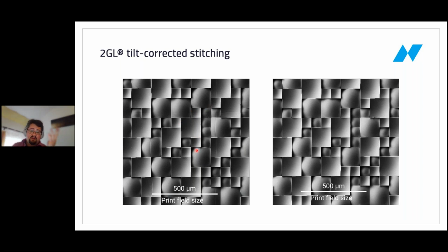So this prohibits us from hiding the stitching just between the lenses, as is sometimes done. So in this case, there's unavoidably some lenses will have stitching seams, and you can clearly see them here in the picture. Now with the same machine, the same design, the same scaling, everything the same, the only difference is we switched on the tilt corrected 2GL stitching. And you can see here, and this was stitched in the same position, but the stitching seams are completely invisible, and they're also invisible in the picture.